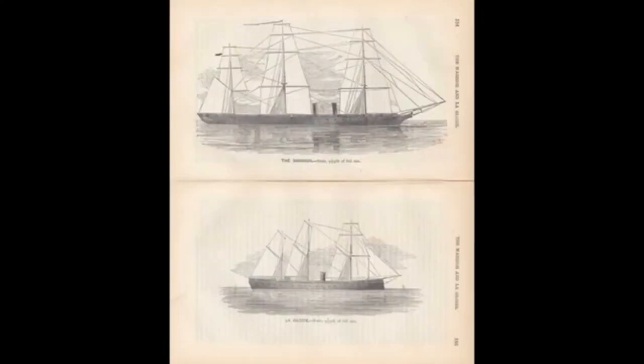The wood backing also reduced the chances of penetration by distributing the force of the impact more widely across the plate than the metal plate alone would have done. Now, both ships did have some issues. Gloire's wooden hull flexed and strained at sea under the load imposed by the iron plating as well as its own natural mass, and the screws that were used to fit the iron to the wood showed that they were a critical point of failure under fire or indeed under heavy load.